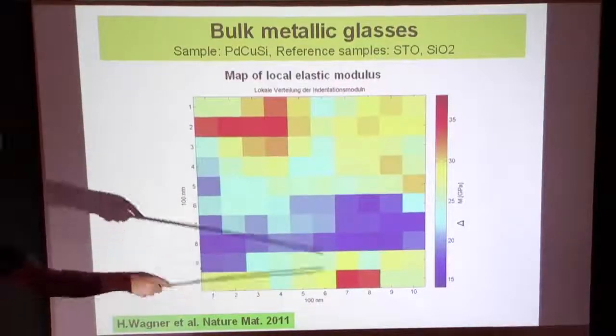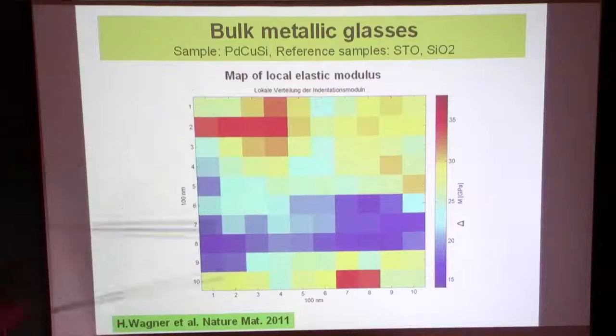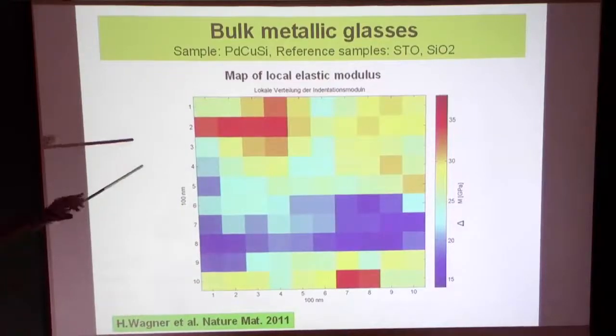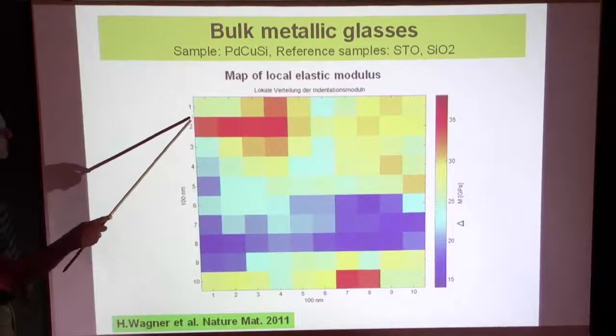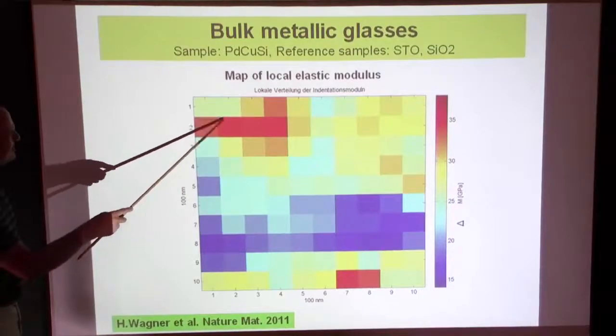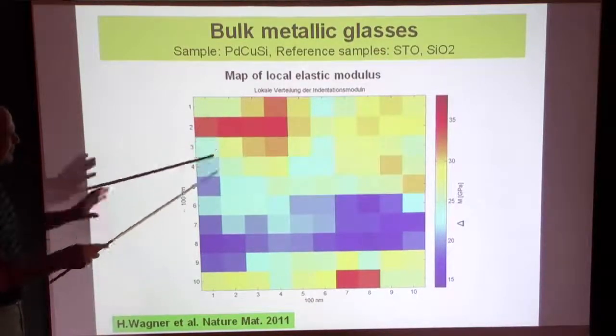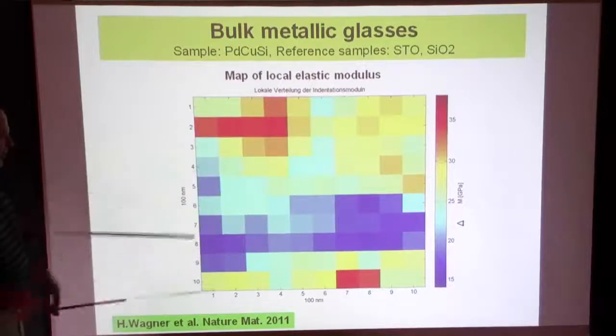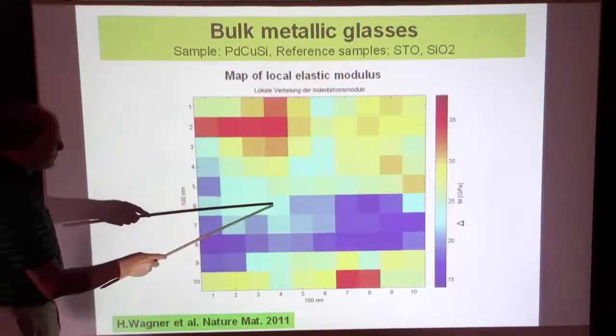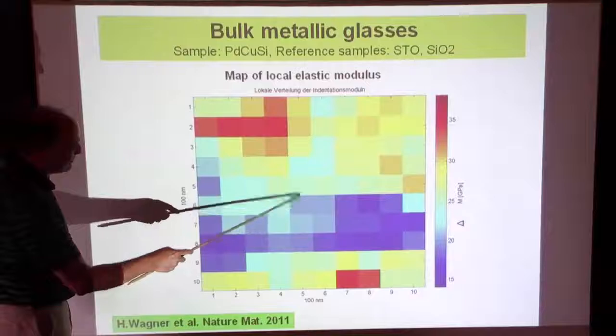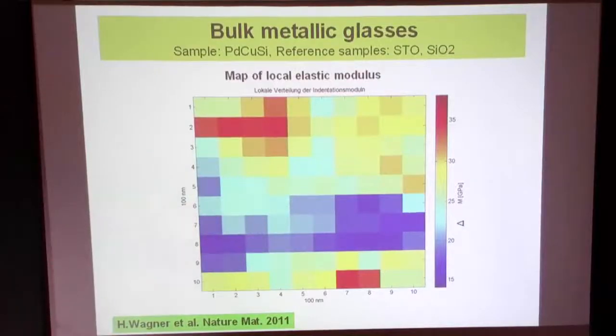And this is 100 by 100 nanometers, so each one is a 10 by 10. This color is meant to be that we make many measurements in this area, and then we assign one color to it, more or less. So it's not meant that this color and that is really sharp interfaces between the two. It's just color coding, just more graphics. Okay, that's to say what is in this region, and then you have an average of all the measurements, and then the other one. So these are the absolute deviations from the average.